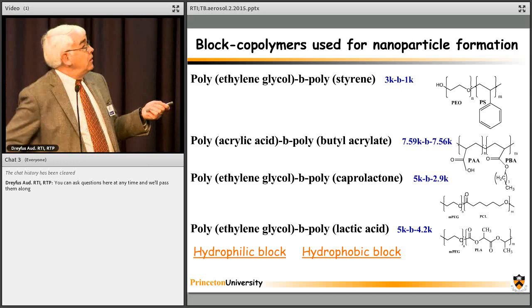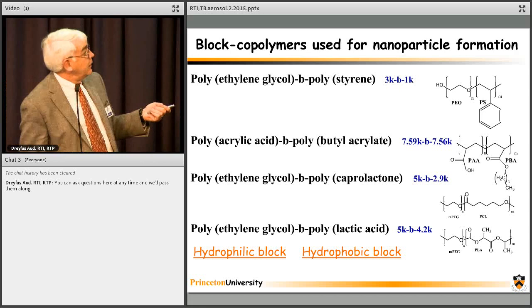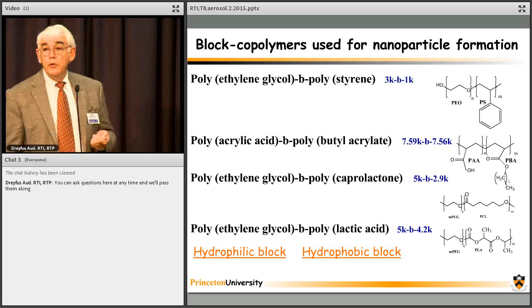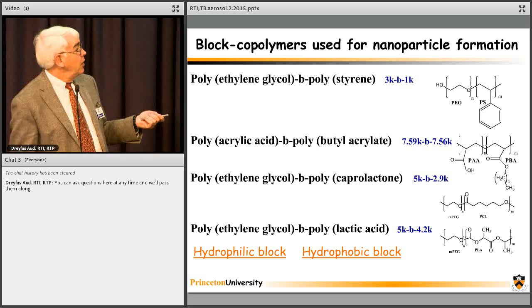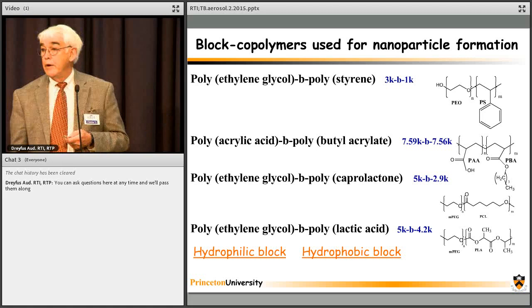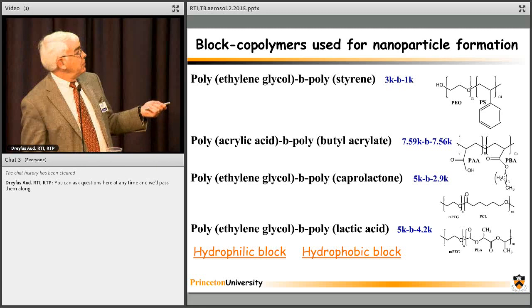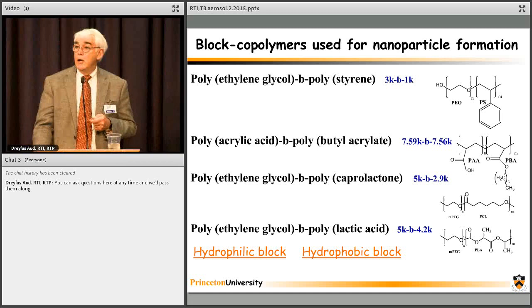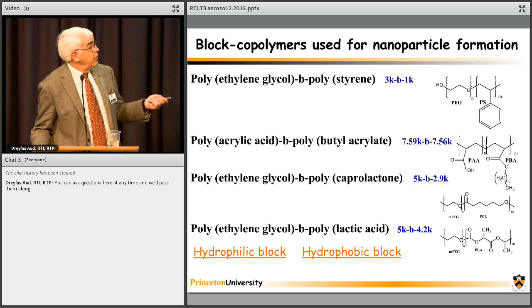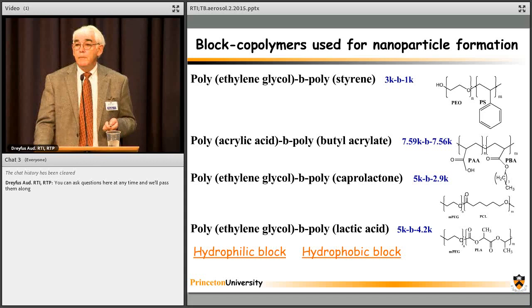The hydrophobic group can be anything from polystyrene to polybutyl acrylate. Most of our collaborators in the medical field want to use biocompatible things, which will ultimately hydrolyze away over a period of about a month. So polycaprolactones and polylactic acid materials will give you the hydrophobic anchoring block that will finally hydrolyze away. The hydrophilic blocks can be polyacrylic acid, but most of what we use is polyethylene glycol. It's a standard way of passivating a cell surface, because proteins will not adsorb on that dense PEG layer. The PEG molecular weight, and we'll show you data in a minute, is anywhere from 2,000 to 5,000, and the anchoring block is usually about 1.5K to maybe 7 or 8K.